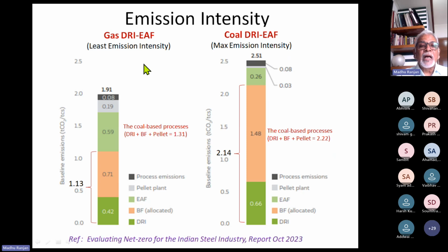Here the two towers are, one for gas-based DRI production in combination with electric arc furnace. This one has the least emission intensity so far as India steel is concerned. And the right side is that of, instead of gas, the coal-based DRI production and electric arc furnace for steel making. And this one has the maximum intensity, 2.51.